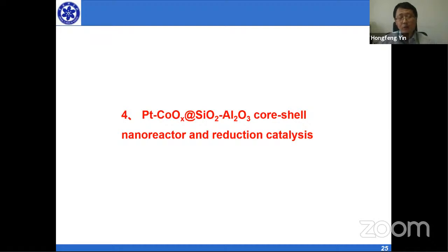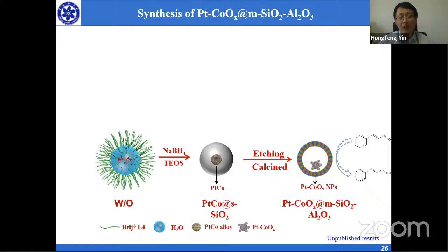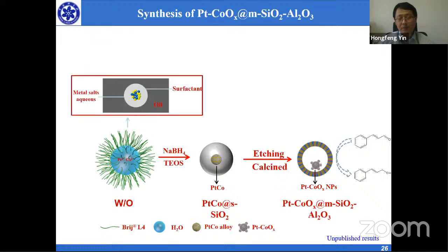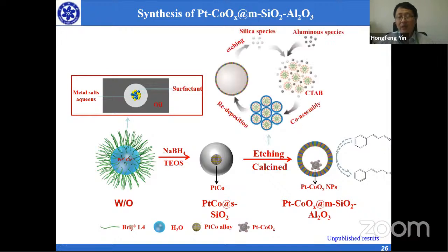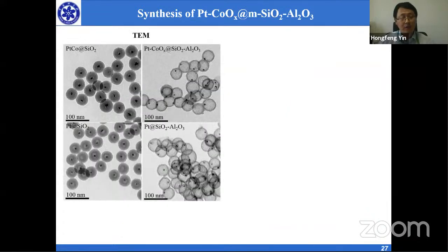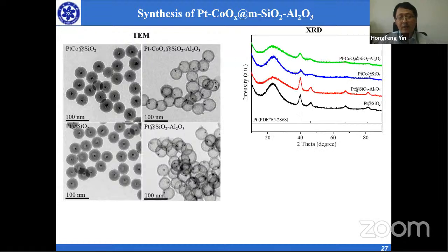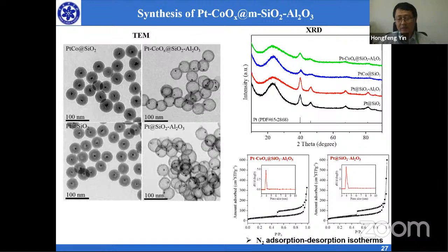For the shell, we also did work to change the shell from pure silica or zirconia into a silica-alumina complex. With the reverse micelle procedure, we can prepare this platinum cobalt nanoparticle with silica as shell, and by etching and introducing alumina species, we can form platinum cobalt oxide as core, and the silica-alumina shell nanoparticle. From TEM, you can see it has very good shape, and also XRD and BET. This structure has a pore size around 4 nanometers and a particle size around 40 nanometers.